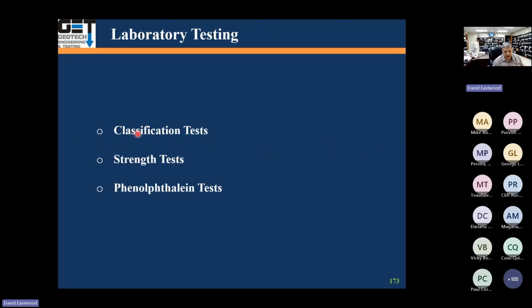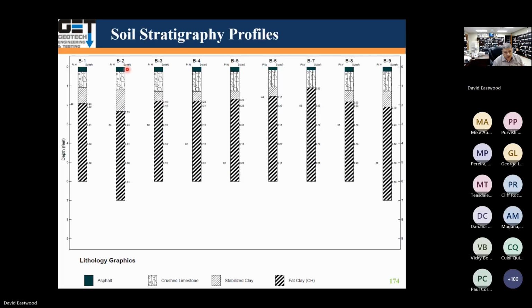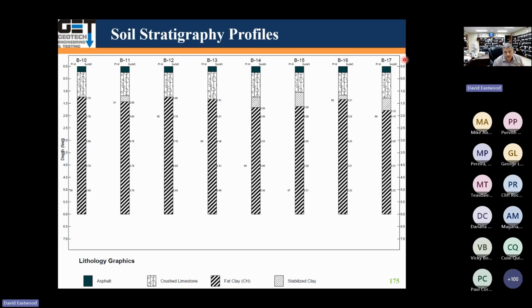We did lab testing, classification tests, strength tests, phenolphthalein tests. You plot the borings, B1, you got the asphalt. Below that, you got crushed limestone. Below that, you got stabilized layer. Below that, you got fat clay. B2, you had asphalt, crushed limestone, stabilized layer. You can see that the stabilized layer here is going to vary all over the place. Same as with the crushed limestone base. These are B1 through B9. This is B10 through B17.